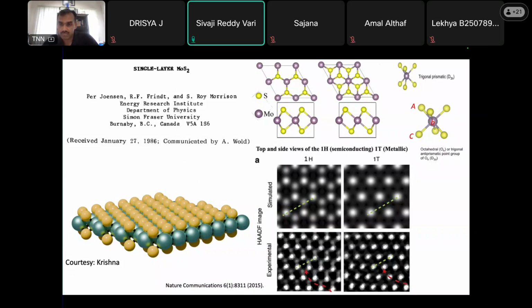Okay, sir. From the experiment point of view, suppose I want only the semiconductor phase, I don't want the metallic phase. How to control that? So basically, in monolayer MoS2, the 1H phase is thermodynamically stable. So most of the time you end up with semiconducting MoS2 when you go to monolayer, just pristine MoS2. The 1T or 1T prime phase is not very easy to get and stabilize unless you introduce some strain or so. So most of the time it will be semiconducting only. Okay, sir. Thank you very much.